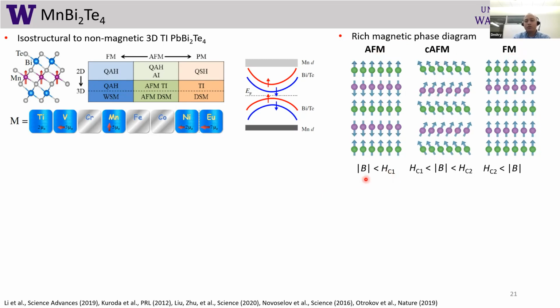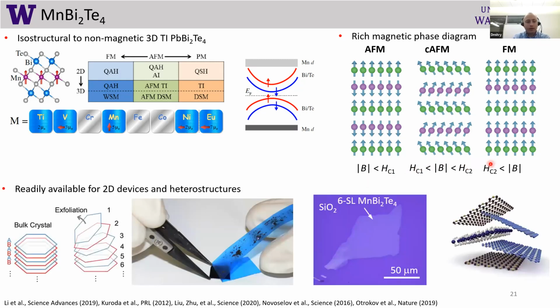But essentially, depending on external magnetic field, you can change the magnetic state of the system, and there would be different physics. And for us, people who work with 2-dimensional materials, the good thing is that we can exfoliate this material and essentially get to several layers thickness. So in this case, I'm showing you an example of a 50 micron size domain of manganese bismuth telluride on silicon dioxide. And it's large, it's flat, and now we have access to high crystalline quality. So with Scotch tape, you can get this flake probably within half a day.